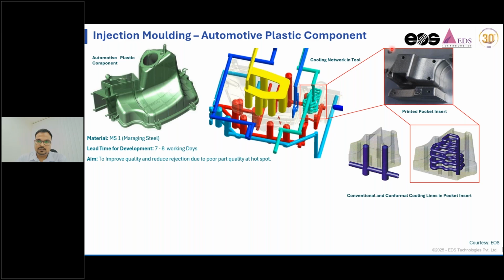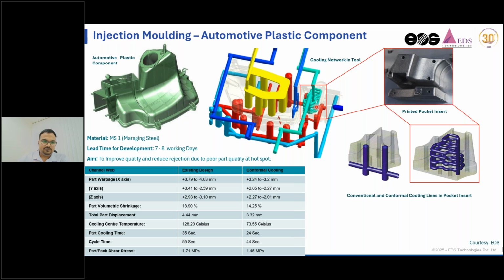with the conventional line going to the conformal cooling line, and this is the 3D printed insert. You can see, this insert goes into the tool, and the direct benefits were the warpages were reduced, the shrinkages were reduced, the deformations that we call displacements were reduced, and the cooling time dropped down from 35 seconds to 24 seconds, and the cycle time also overall dropped down. So around 30% of rejections in this case were reduced, and productivity was increased by 20% in the plastic injection molding.